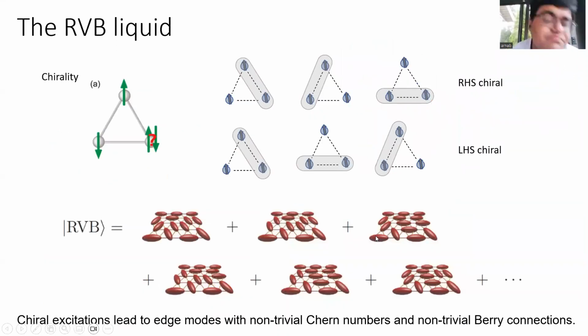So how do you get to a spin liquid? To get to a spin liquid, you will have to somehow ensure that even though you have very strong interaction between all the bonds, they are not able to order. And one way to achieve that is by using a mechanism called frustration. So frustration, in a very simple picture, is when you have three spins, let's say, which are antiferromagnetically interacting with each other on a triangle. So you basically have a bipartite Hamiltonian on a tripartite lattice. That's one of the ingredients that you have.